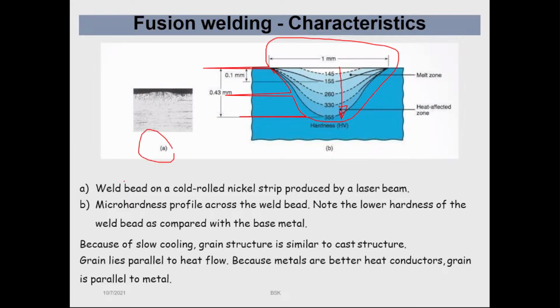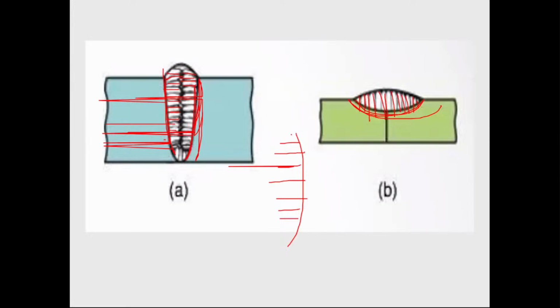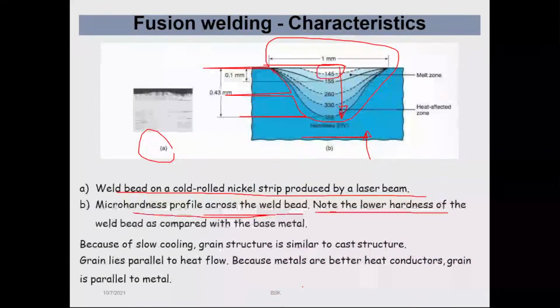The first one is a weld bead on a cold roll nickel strip produced by laser beam. That is a separate one. Micro hardness profile across the weld bead. Note the lower hardness of the weld beads compared with the base metal. So in this area the hardness is low. In the other areas, you can see that the hardness is high. Because of this slow cooling, grain structure is similar to the cast structure. Grain lines are parallel to the heat flow because metals are better heat conductors. Grain is parallel to the metal, right? That is something I mentioned earlier. It grows along the same line like this. This is a separate story; it's about hardness, okay?